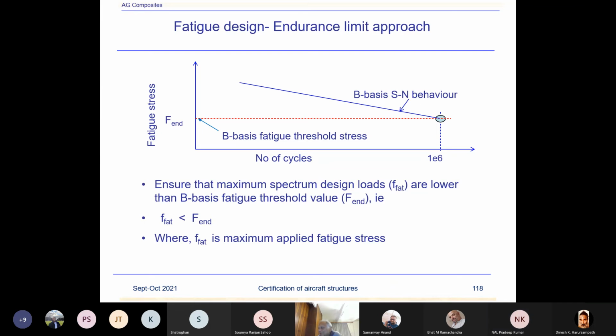Yes, stress ratio is -1. Usually we generate the curves for R = -1, but sometimes that becomes conservative, and then we try to see if we can apply the proper spectrum, because R equal to -1 gives the lowest curve. Yes, it's the most damaging. So generally we try to use R equal to -1, but in some cases, if the margin is negative because it's conservative, then we look into whether we are being realistic, whether R equal to -1 is realistic or we are being too conservative. Then you try to look into maybe R equal to -0.5 or -0.7, depending upon the design considerations.